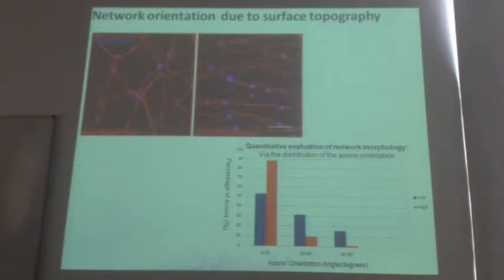So here is a quantification of the development of this type of network on top of low roughness and high roughness. As you can see, here is the percentage of axons that are oriented at an angle between 0 and 30 degrees, 30 and 60 degrees, and 60 and 90 degrees. The blue is the low roughness and the red is the high, so you can see that there is a preferential orientation in the high roughness compared to the low roughness substrates.